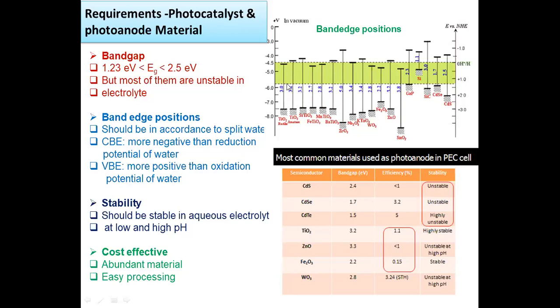So 3.2, let us say TiO2, 3.2. If you want to excite an electron from this valence band to the conduction band, you need to irradiate with a photon which has 3.2 electron volts, which actually lies in the UV range, and that makes life complicated. Whereas what we need today is for sunlight to directly do this task, not UV, and that is the reason we want something like 2.5 or maybe 1.7, in that range, some photocatalyst which can straddle this whole redox level of water, and in that way it can be suited.